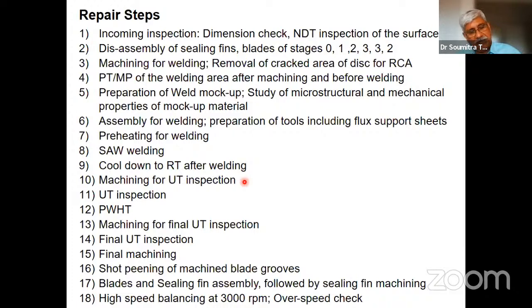And I'll show you about some of the developments that have been there in recent times to do these careful inspections. And from the inspection, making sure that you can go in for a post-weld heat treatment. After post-weld heat treatment, again doing an inspection before doing a final machining. In fact, what we found is after the post-weld heat treatment, that there were 3 defects in the weld metal that was left. And through calculations, we found that at least 2 of the defects would be removed when the machining of the T-slots would be made in the weld-laid material. So that was not of concern, but one of the defects would lay there.